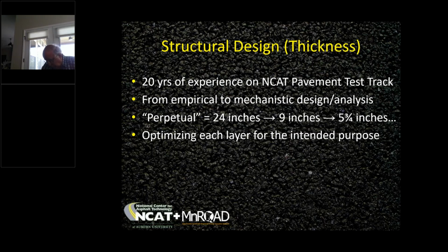But that's a very, very positive message and good information that came from the research that we did here at the track. And at the core of this perpetual concept is optimizing each layer for the intended purpose, and I alluded to this earlier. At the bottom of that lowest layer of asphalt, it needs to be crack resistant so you don't get a bottom up fatigue crack. In the middle of the pavement structure, if you put a stiffer inner layer, like you can do with higher percentages of reclaimed and recycled materials, you reduce the deflections, which reduces the possibility of bottom up fatigue cracking. And then you put a durable rut resistant surface on that, and you can get a thin pavement that can last forever and do it in a very cost effective way.